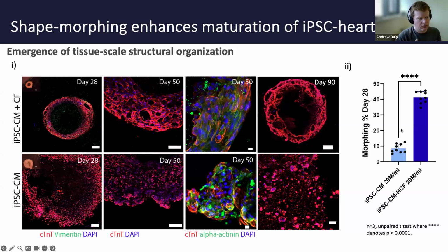So we got about a 40% reduction in the diameter. In a control static group that was not morphing, we did this by only encapsulating cardiomyocytes in the tissue. So this had no fibroblasts. And we found that the tissues did not shrink as much, so it was about 10% morphing. And you can really see that had a detrimental effect on the cell alignment. So they're very rounded. The cardiomyocytes are there and they're alive, but they don't have that nice anisotropy that we see in this top panel. And you can see that the sarcomeric protein is much more disorganized, and that even stayed up to day 90 in culture.